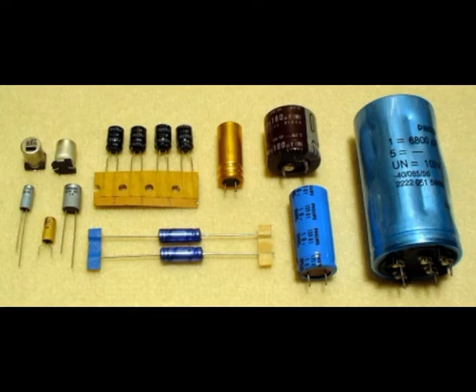The graph at right shows the behavior of the electrical parameters of aluminum electrolytic capacitors with non-solid electrolytes due to evaporation of the electrolyte in a 2000 H endurance test at 105 degrees Celsius. The process of drying out is also detectable by weight loss. After this endurance test, the specified parameter limits to pass the test are, on the one hand, no total failures,